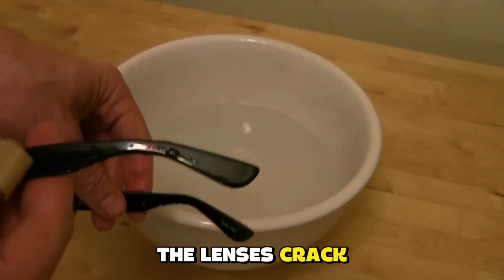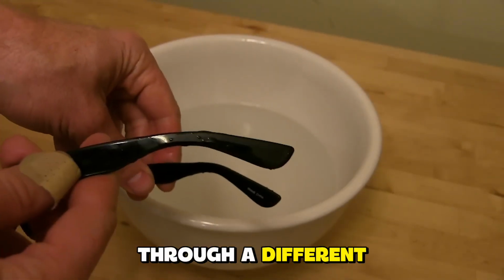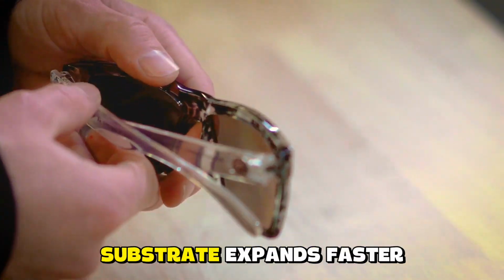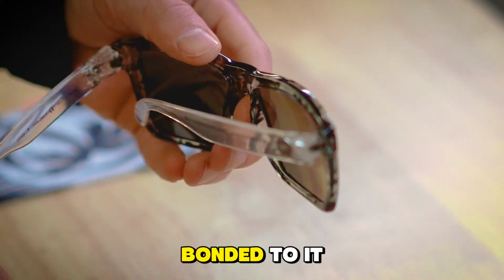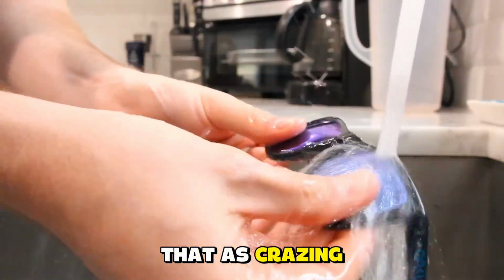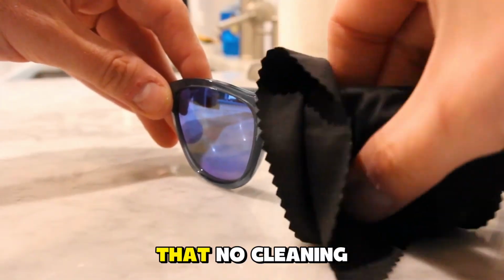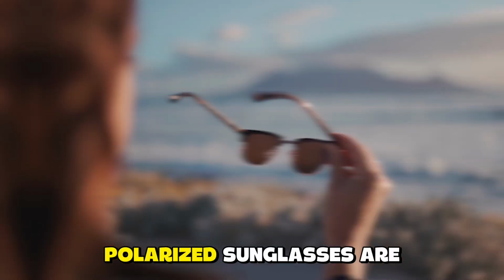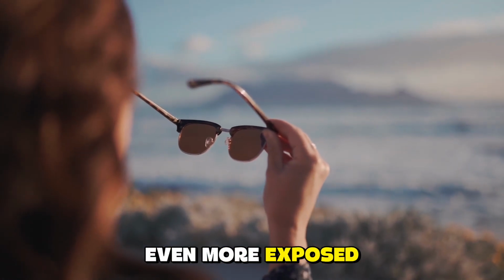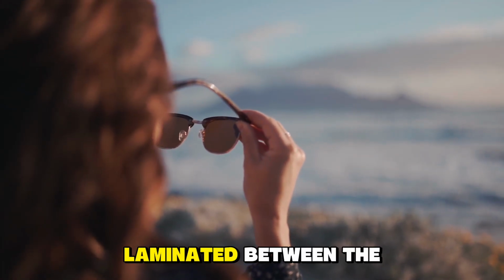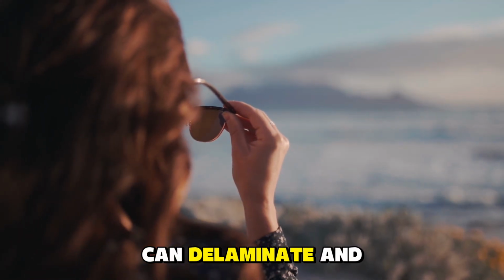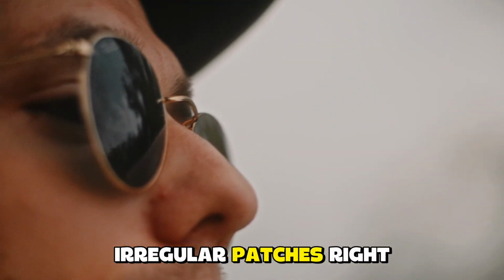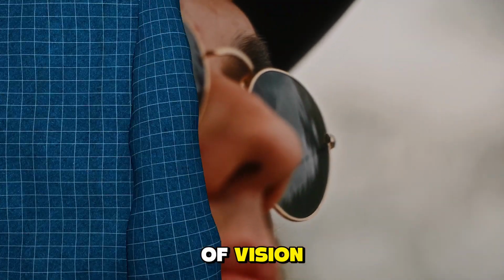So the frame softens and sags under its own weight without looking obviously damaged. The lenses crack their anti-reflective coating through a different process, where the polycarbonate substrate expands faster than the coating bonded to it, and you see that as crazing or a sudden glare and crease that no cleaning cloth fixes. Polarized sunglasses are even more exposed because the polarizing film laminated between the lens layers can delaminate and leave dark, irregular patches right across your field of vision.